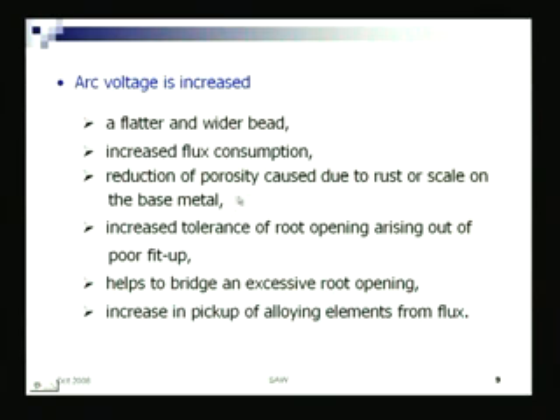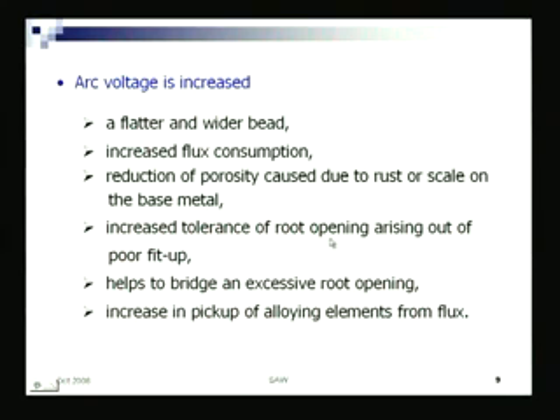There is also reduction of porosity caused due to rust or scale on the base metal - that is an advantage. Increased tolerance of root opening is another benefit. When welding, if the root opening is not very uniform, a wider bead is preferable, because where the gap is more, it covers that, giving a higher tolerance level of the root opening. That is what helps bridge an excessive root opening.